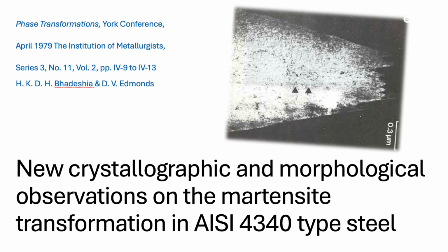Okay, that makes sense for the laths in a packet. But what about the plates? What are their boundaries like? The plates are different. Their boundaries are described as a polygonized dislocation arrangement. Polygonized dislocation. Sounds complex. It is. Think of dislocations as tiny imperfections or line defects in the crystal structure. Polygonized means these defects have arranged themselves into a more ordered, structured boundary, almost like a tiny grain boundary itself. So not a simple low-energy habit plane like the laths use. No, it implies the plate formation involves a much more complex mechanism for managing that transformation strain. It's a higher energy boundary structure.